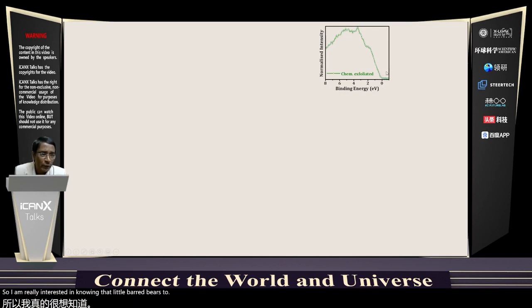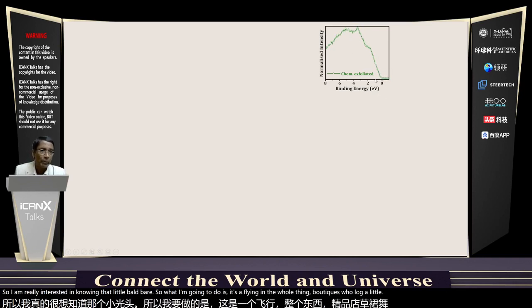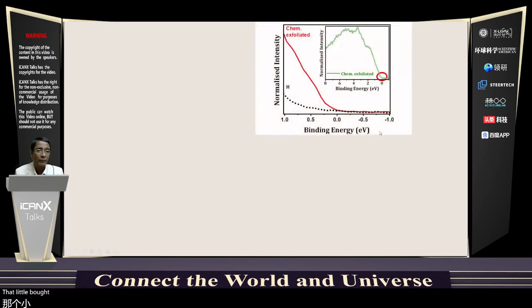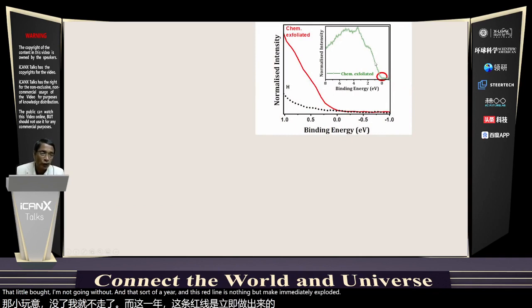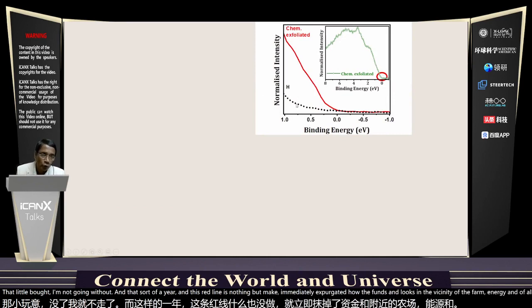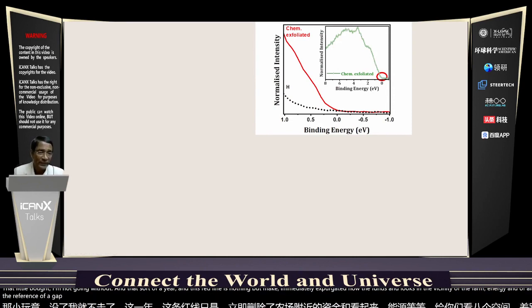So what I'm going to do is, instead of showing you the whole thing, pull out a little part from here and look at it more closely. That little part I'm now going to pull out is shown over here. And this red line is nothing but my chemically exfoliated system, showing how the valence band looks in the vicinity of the Fermi energy. And I've also shown you the H phase, the gap system, to show you the reference of a gap, no intensity at the Fermi energy.